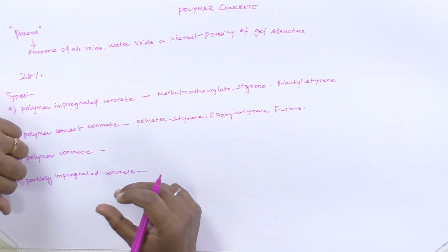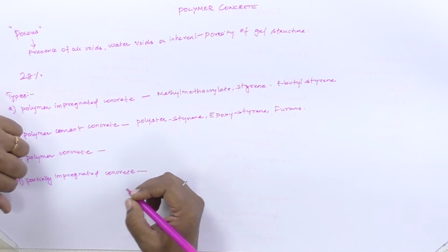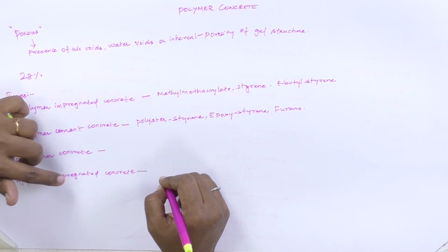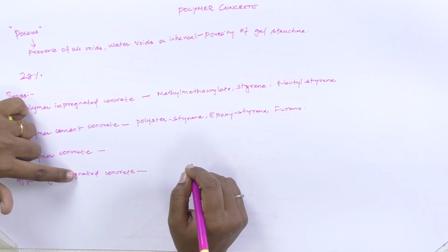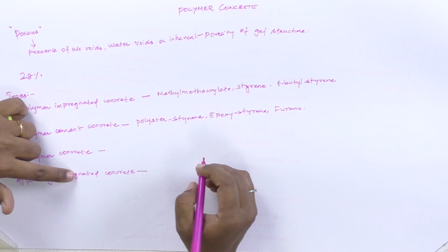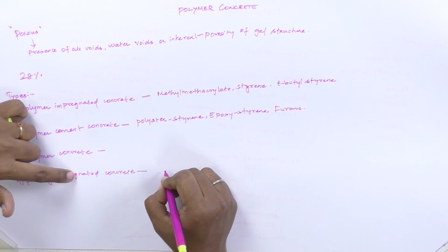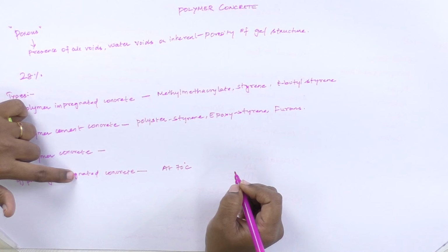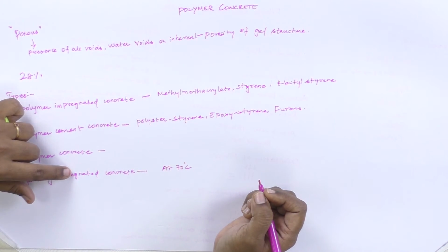It can be produced by initially soaking the specimen in a monomer, then sealing the specimen under hot water at 70 degrees Celsius to prevent any loss due to evaporation.